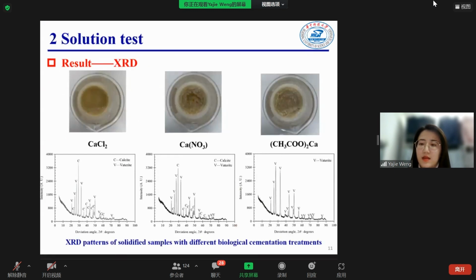After that, the mineralized precipitate products were analyzed by XRD. We can see that calcite and vaterite exist in the calcium carbonate crystals induced by calcium chloride and calcium nitrate, while only vaterite exists in calcium acetate. In the calcium chloride and calcium nitrate samples, the induced calcium carbonate crystals are mainly calcite. By comparing the two, we can see the calcite peak of calcium chloride is higher than that of calcium nitrate. That is, the crystallinity is better.